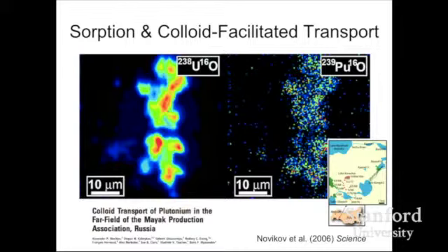Even if the normal thermodynamics of the solution don't hold, plutonium has the property, as do the other actinides, of being able to stick on iron oxides, small colloids, very small things held in suspension in water. And so you can see the uranium stuck to these, and plutonium stuck to these iron oxides. This is 10 microns across, so they're very small. And so this is another transport vector.